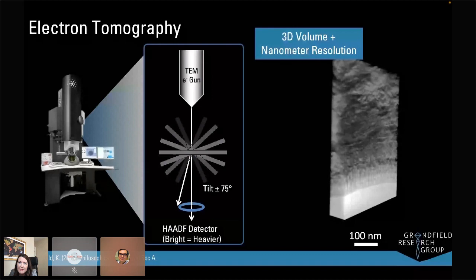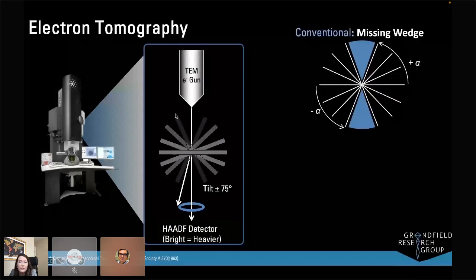And that's something called the missing wedge. So you'll notice in this cartoon, there's an area we can't tilt to. There's not enough space in the microscope for us to tilt a perfect 180 degrees. So we result in this area that we can't access and probe, and this causes some stretching in the 3D reconstructions.